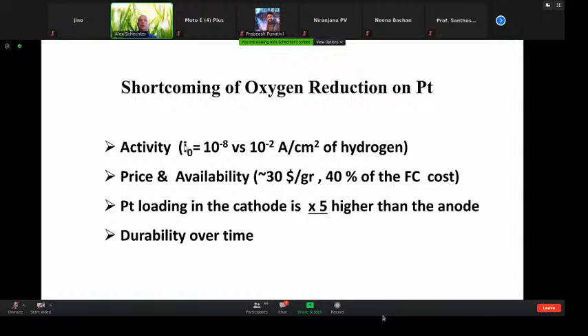The activity, the exchange current density, which is a measure for the kinetics of the reaction, the I0 is 10 to the minus 8, versus if you compare that to hydrogen, is 6 orders of magnitude lower than that of hydrogen. The price and availability of platinum we have discussed, $30 per gram, changing, and around 40% of the fuel cell cost. And platinum loading is 5 times higher in the cathode, and given all these, there is a severe problem of durability of platinum over time.